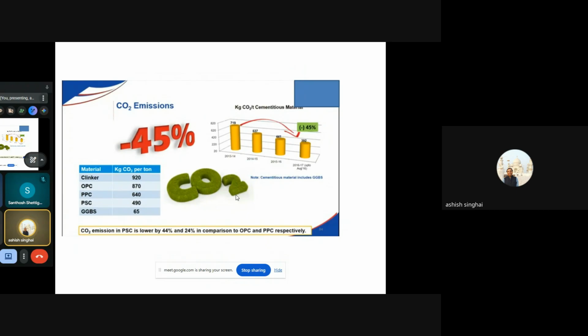Slag cement has the typical ability to reduce the carbon dioxide emission by 45% as compared to OPC. In the same context, LC3 will also help us in the reduction of the carbon dioxide emission to the extent of almost 42 to 45%. So these are the figures that help us in making our choice towards either blended cement, LC3, or possibly geopolymer concrete, which doesn't have any OPC content.